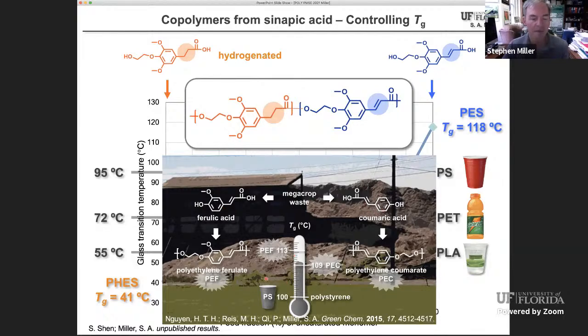So those give polyethylene ferulate and polyethylene coumarate with slightly lower glass transition temperatures. For polyethylene ferulate, you get 113. For polyethylene coumarate, you get 109. So it seems like what we're learning here is that by adding 1 or 2 methoxy groups, you get a slight boost in the glass transition temperature of the corresponding polyethylene coumarate, ferulate, or sinapate polymer.